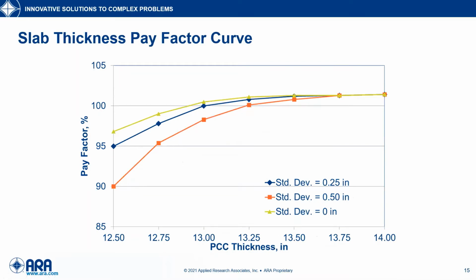And here's another example. This is the values for the slab thickness pay factor. Notice this one looks a little different than the strength. The as designed target thickness for this pavement was 13 inches. And you can see, get my pointer here, a small reduction in thickness results in a significant decrease in service life, as well as an increase in standard deviation. But conversely, that same increase does not result in the same increase in service life. And this ultimately has to do with the pavement design for that section and the various factors that go into that pavement design.